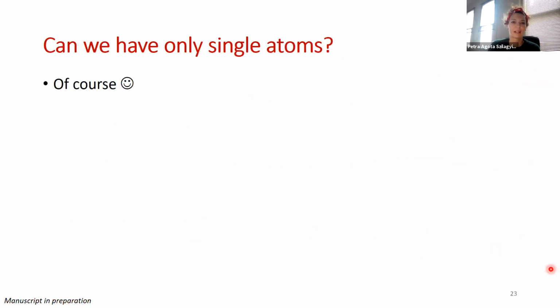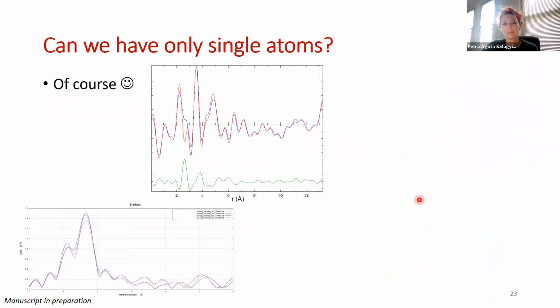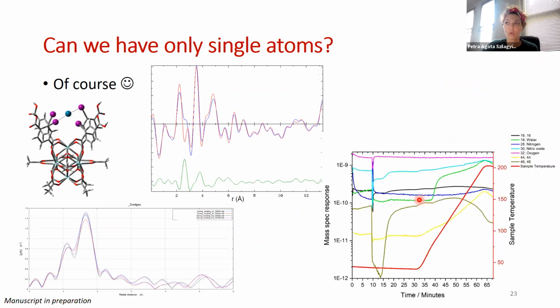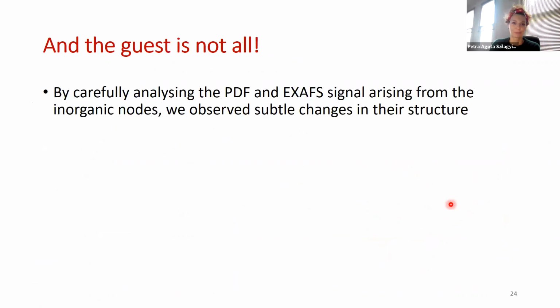And just very briefly, I realized that I didn't have so much time left. I'm just going to briefly run through this, that since then we had been able to come up with a framework that only immobilizes these single naked neutral palladium atoms. And reassuringly, it wasn't active in carbon monoxide oxidation, so we don't have particles. It is somewhat active in the NOx reactions, but it's not particularly selective. So at the moment, we're looking at other reactions these could be explored for.